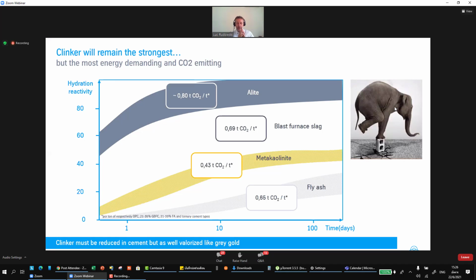Even if the challenge of the alite here, representing the clinker, is that it's emitting the highest amount of CO2 and is the most energy demanding when compared to a possible alternative like blast furnace slag or fly ash, which, as everybody knows, have less resource available. Metakaolinite is an option, definitely, but still alite is showing the strongest hydration and reactivity over time. So that means we will have to reduce the clinker, but still the remaining portion of clinker in cement will have to be valorized. And I use this term gray gold because it will remain in the cement industry.